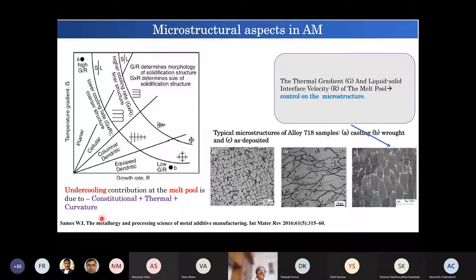There has been, as I mentioned earlier, a map that deals with the kind of microstructure that will get generated in additively manufactured materials. And this is a function of, if you plot thermal gradients and the growth rate, then we can get from equiaxed dendritic to columnar dendritic to cellular to planar, and all have, as I said, very important attributes. Some are good for high temperature property, some are good for cyclic properties, some are good for room temperature tensile strength or something.